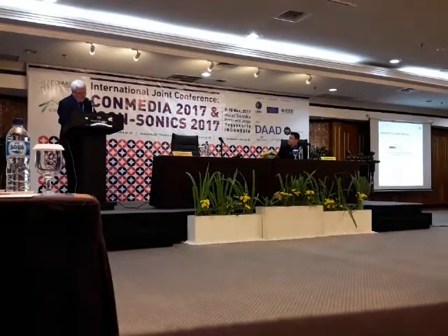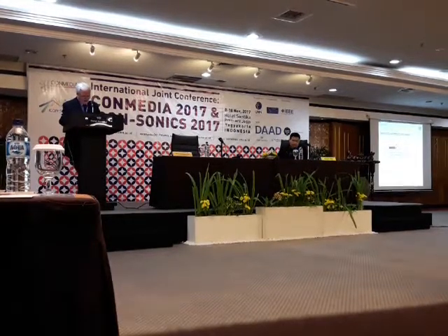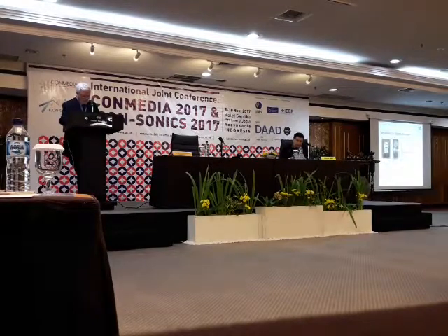And furthermore, you have a magnetostrictive electric conversion principle, which is also very interesting. It delivers a power density of about 7.6 milliwatt per cubic centimeter, but unfortunately it uses galfenol, which is not really cheap as a basic material.